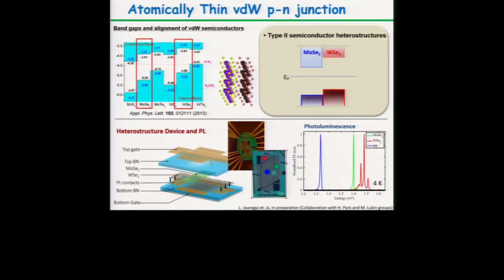And if we also take photoluminescence on the heterostructure, we now see a photoluminescence peak, but at lower energy. Now the recombination is not coming from each of the materials individually; it is coming from the electron in MoSe2 and the hole in tungsten diselenide. Because of the alignment, they have a lower energy, and that's what we observe.